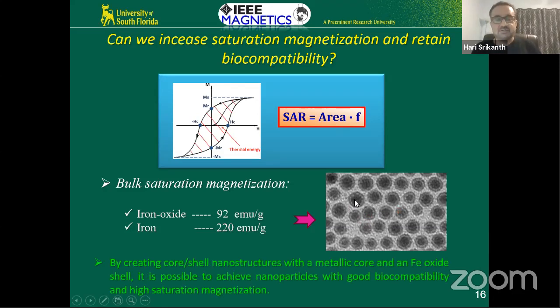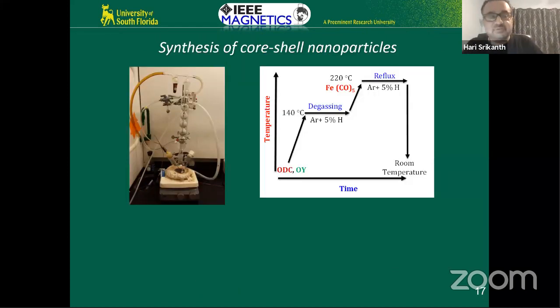However, it turns out, so we can actually do this. We can increase the saturation magnetization. So those of you that are, I know that many of you are interested in the chemistry. So everything that we do here, all the nanoparticles are done by simple solution synthesis, thermal decomposition, solvothermal techniques. And essentially we do that in the lab using iron pentacarbonyl. These are some heat treatments.